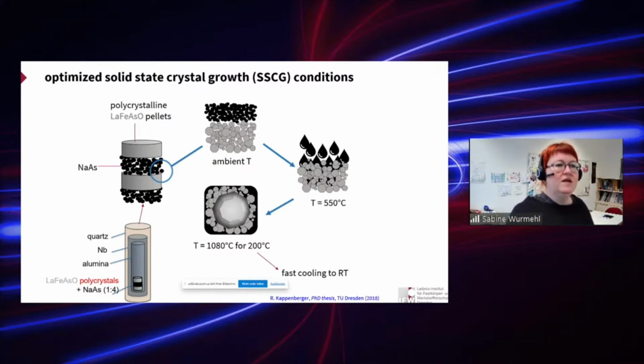If we heat it up to the melting temperature of sodium arsenide, we get a wetting of our pressed pellets. At 1080 degrees C, we are low enough in temperature to not allow the rounding of the facets, but high enough to have a high diffusion coefficient. We allow 200 hours to grow the crystals within the solid pellets, and then we can cool down fast to room temperature.